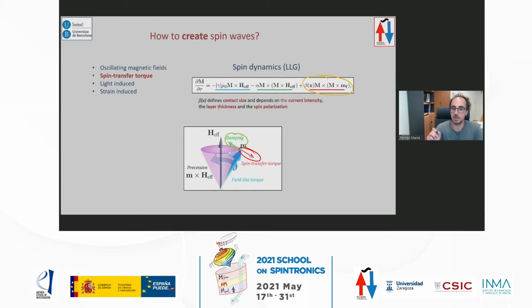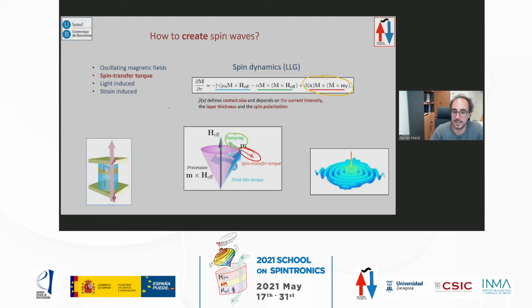So if you have the right geometry, just with the DC excitation, and this is important, before you had to use an AC frequency with the effective field. Now with the DC excitation, you can create an effective negative damping, and that leads to magnetic excitation. So if you do that in a confined area, you have nanopillars, so this is used in memories. But if you do it in an extended thin film, you can create spin torque nano oscillators, and you can create propagating spin waves.